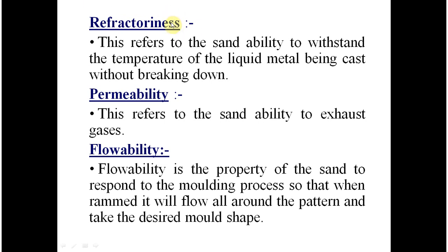Refractoriness refers to the sand's ability to withstand the temperature of the liquid metal being cast without breaking down. For example, some sand only needs to withstand 650 degrees Celsius when casting aluminum alloys, whereas steel needs sand that will withstand 1500 degrees Celsius. Sand with too low refractoriness will melt and fuse to the casting.